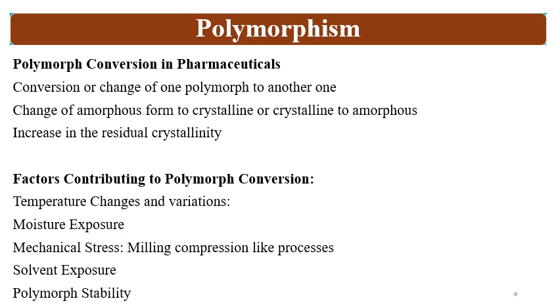The factors affecting polymorph retention and polymorph conversion are essentially the same. During manufacturing, solvent effects — such as in wet granulation — can lead to formation of a different polymorphic form. Temperature changes, moisture exposure, and humidity exposure are key factors. Mechanical stress from milling and compression in solid oral formulation manufacturing may lead to changes in polymorphic form. API milling, micronization, and nanonization can also impact polymorphism.